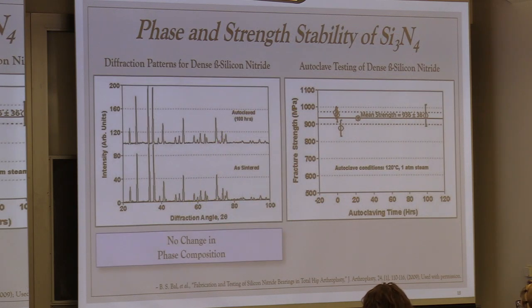Okay, and this slide just highlights that. An early study that was done shows that if you take silicon nitride and you subject it to autoclaving conditions for an extended period of time, up to 100 hours or more, there's no change in phase composition, and the strength of the material basically remains constant.